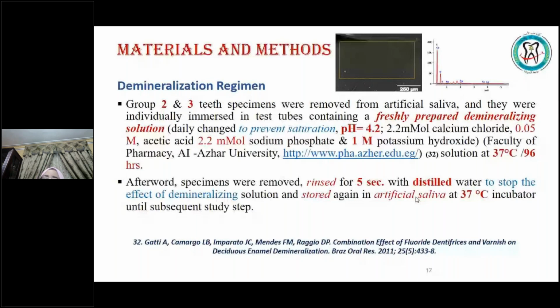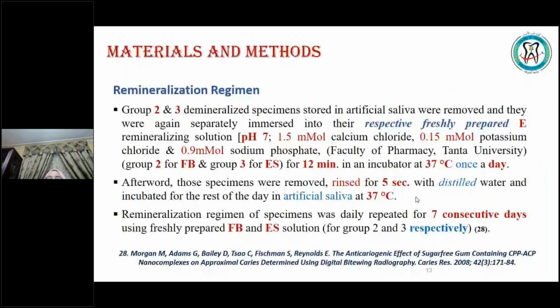The remineralizing regime. Going to the remineralizing regime for group 2 and 3, it will be different. The demineralizing regime was the same, while the remineralizing solution will differentiate between group 2 and group 3. The group 2 and 3 demineralized specimens were stored in saliva individually, where they were removed and separately immersed in their respective freshly prepared enamel remineralizing solution. Here the remineralizing solution pH was 7 for the eggshell and for the fishbone remineralizing nanoparticle solution used in the study, and it is incubated at 37 degrees centigrade once a day.